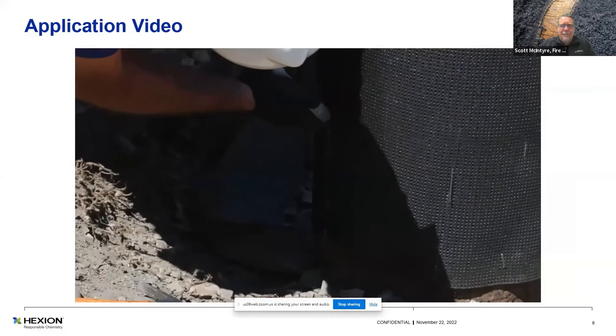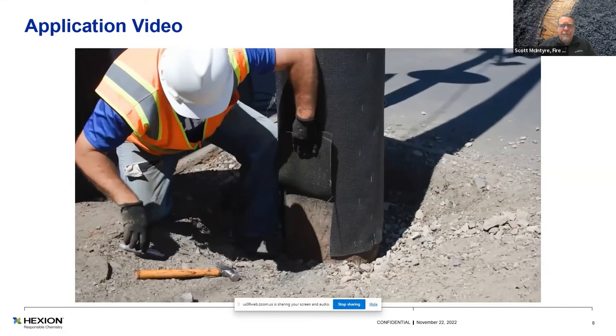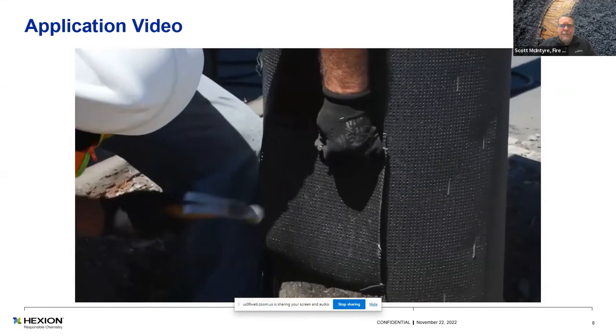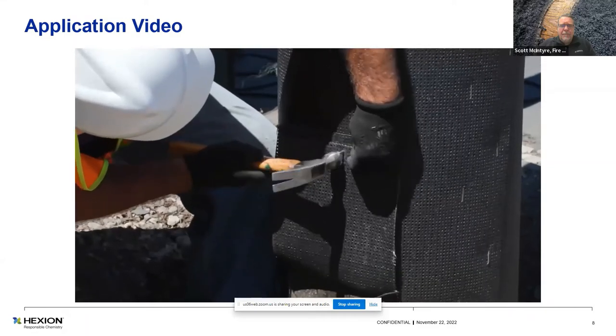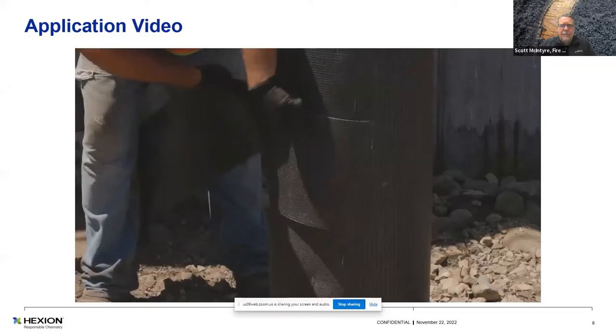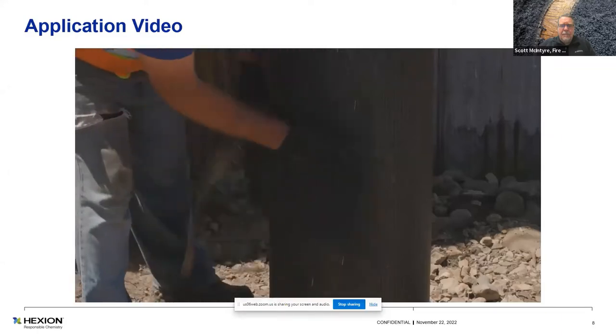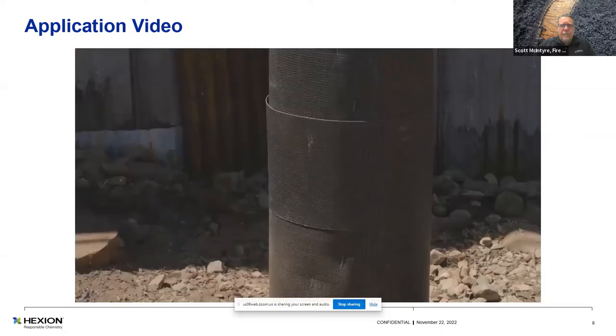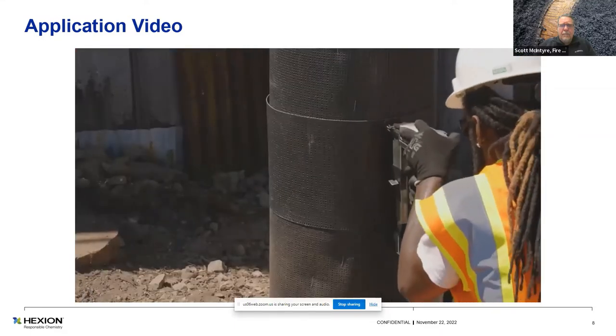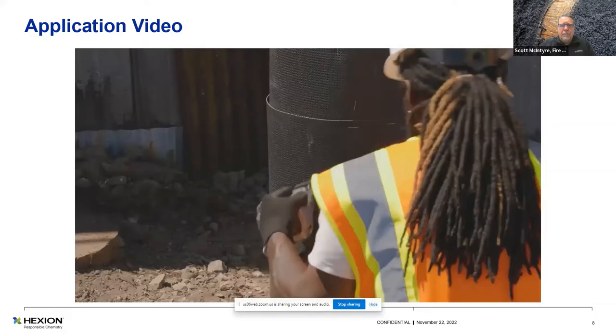When it comes time for pole inspection, you can cut a flap to expose the pole surface. After inspection, the flap can be resecured using galvanized roofing nails or stainless steel staples. If the ArmorBuilt wrap ever becomes damaged in service, cut a patch of new material with a 3-inch overlap in all directions beyond the damaged area and attach the patch using the vertical seam 2-row fastener pattern. The top and bottom circumference of the patch must also be nailed or stapled.